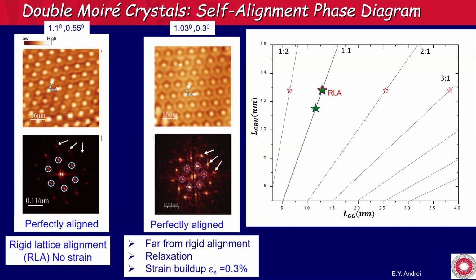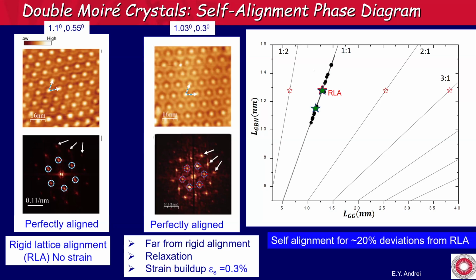And you can see by looking at the Fourier transform, you can see the inverse lattice vectors, and they are way away from the rigid lattice alignment, and we can calculate the strain is about 0.3%. And then we look at more samples, and we have a whole array of them, and they're all along this line, and they're way far, up to 20% deviation from rigid lattice alignment. So it looks like this crystal likes to relax to the 1-to-1 alignment.